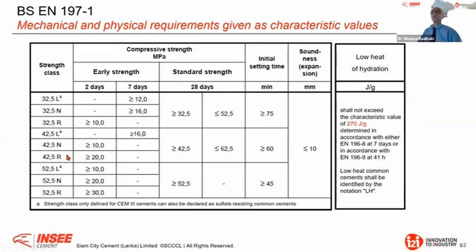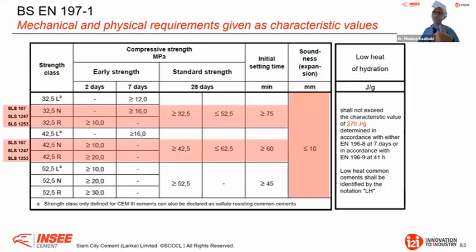We miss them. Now, when it comes to mechanical and physical requirements given as characteristic values, we know very well in Sri Lanka 32.5 and 42.5. We know the N class and the R class because this is our Sri Lankan standard. If I take the 107, the 1247, and the 1253, they are within this range of compressive strength class. They have added in the European standard only for CEM III cement, high slag cement, the 32.5 L, where the requirement at 7 days is 12 MPa and not 16 MPa, for the 32.5.